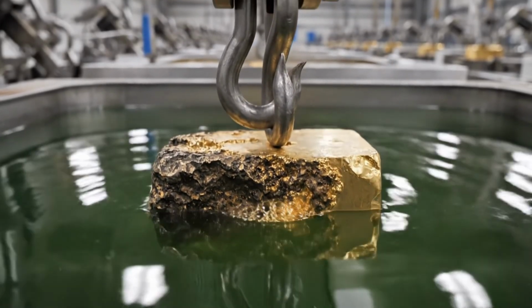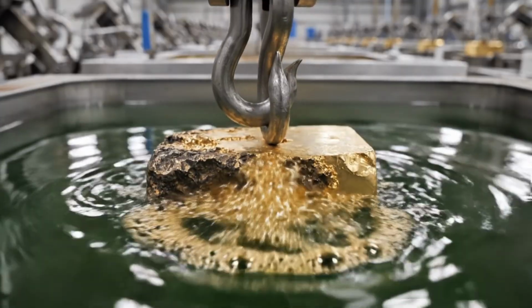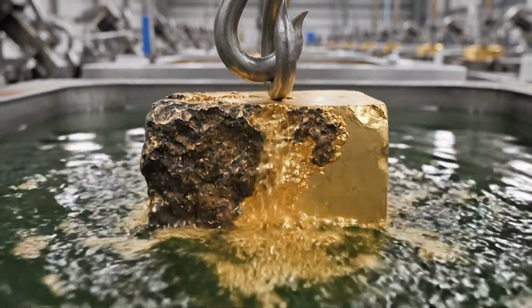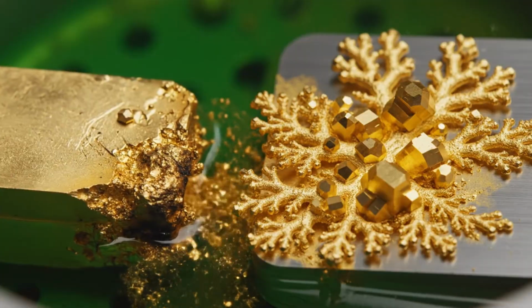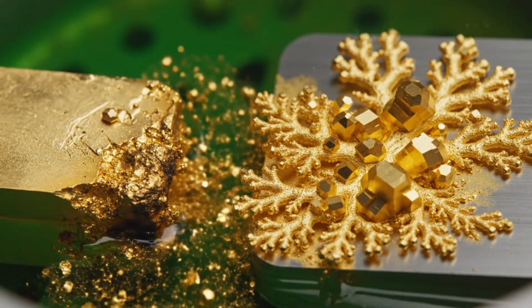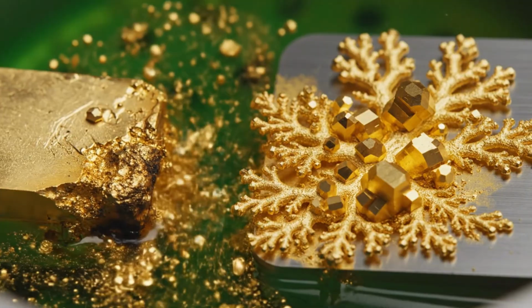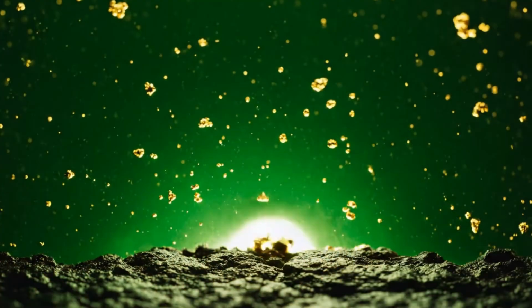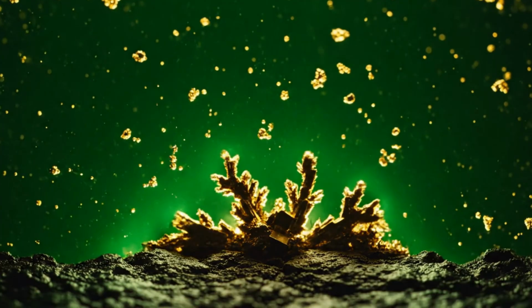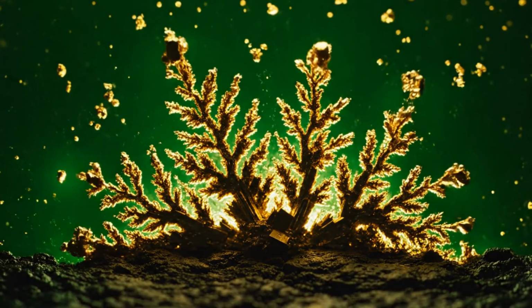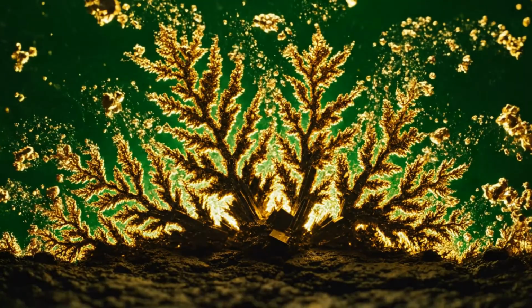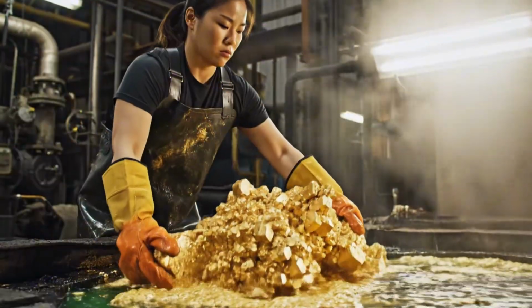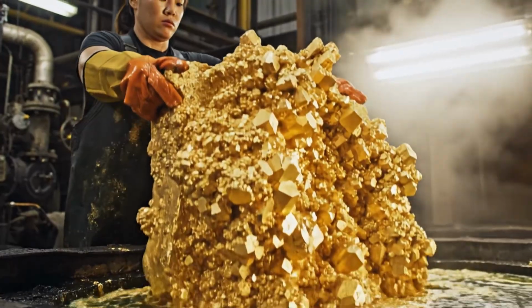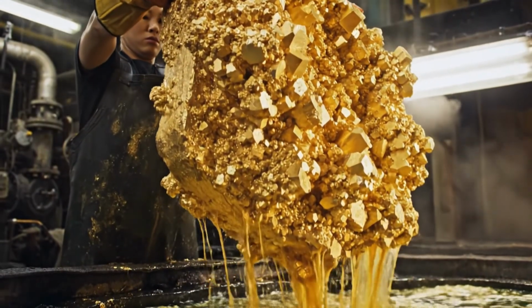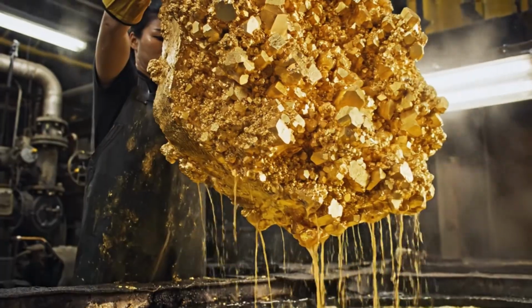They must undergo electrolysis, a bath where electricity strips away the final stubborn traces of silver. Anodes dissolve slowly in the solution, migrating gold atoms to the cathode sheets, building up a layer of 99.9% purity. It is a silent migration of atoms, invisible to the naked eye, but essential for achieving the investment-grade standard required by global banks. The cathodes are removed from the tank covered in high-purity gold crystals that sparkle under the factory lights like jagged and frozen sunlight.